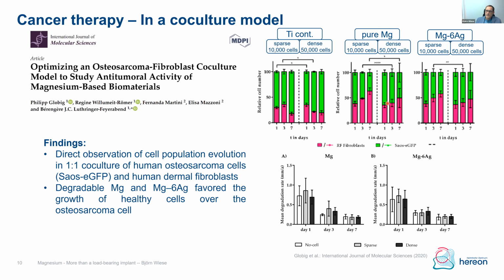But the degradation products of magnesium and these magnesium silver alloys show that the numbers, the green bars, get smaller with time. The numbers of sarcoma cells get reduced in relation to the healthy fibroblast cells. And this is independent of the alloy, whether it's pure magnesium or magnesium 6 silver. That means degradable magnesium and magnesium 6 silver favor the growth of healthy cells over the osteosarcoma cells. So it's somehow what we want to see.